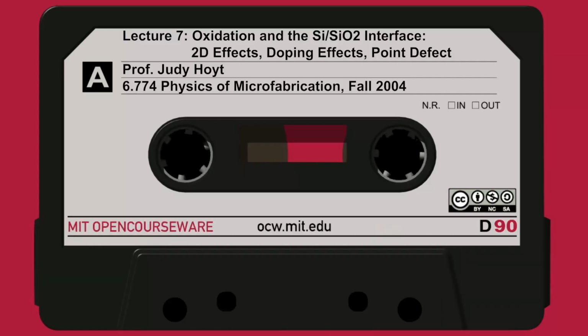But you would see this white ring here is the silicon that was initially oxidized, and the blue ring all around it is the oxide that grew on the inner part of the cylinder and the outer part of the cylinder. And then you can vary the cylinder size. You can create a whole lot of these cylinders on the same wafer and look at how the oxide grows, what its oxidation rate is as a function of the radius of curvature. So it's a very nice sort of scientific experiment to look at these dependencies.